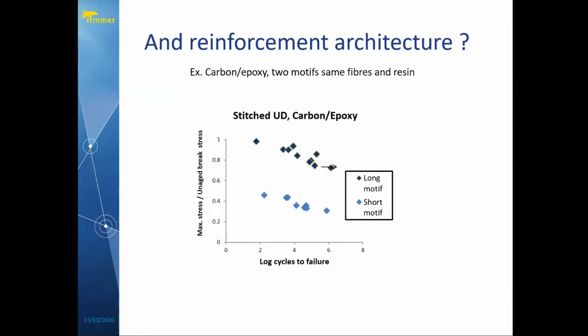Next slide, please. And the third parameter is reinforcement architecture, which was something which we hadn't really considered, but I think Erwan showed this slide as well. When we first started on the Sabella project, we looked at a particular fabric and we ran some first fatigue tests, and we were getting very low fatigue performance. These blue plots here. And then when we looked at the damage mechanisms, we could see that the damage was initiating at the weft fibers, which had a very short repeat element.